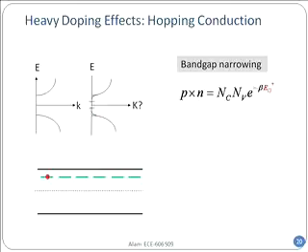When light comes in and shines on it, the jump will be a little bit less. So the first thing to check, notice, is that the law of mass action, P multiplied by N, is no longer the band gap of silicon, 1.1 eV, but rather it is the effective band gap, EG star. The EG star is the top of the green and the bottom of the green for the conduction and valence band. That reduced level is the effective band gap. And so you will see all your relationships will change a little bit.